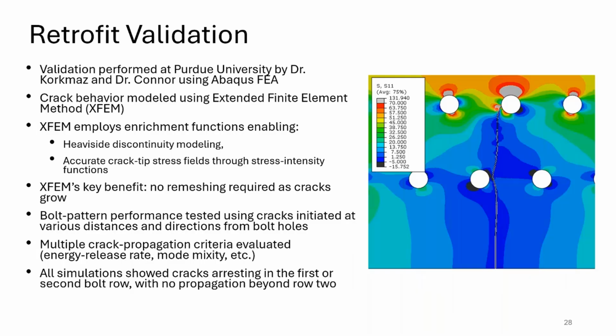In addition, it has a crack propagation scheme so that if you meet a certain criteria, the crack propagates. We sent a series of bolt patterns to Dr. Korkmaz and Dr. Connor at Purdue University, and they provided validation using the extended finite element method. What we found is that the majority of the cracks tended to end in the first row of bolts, with only some extending into the second one and none of them going into the third one. During this evaluation, they used different crack propagation criteria with different energy release rates and different mode 1 to mode 2 propagation ratios as well, trying to consider all possible fracture propagation conditions.